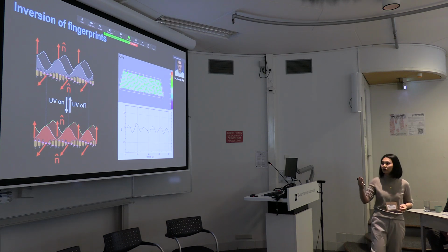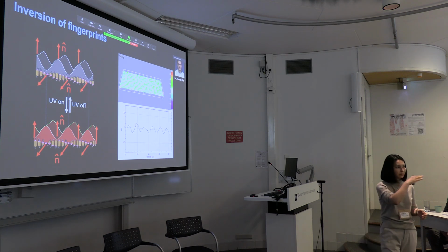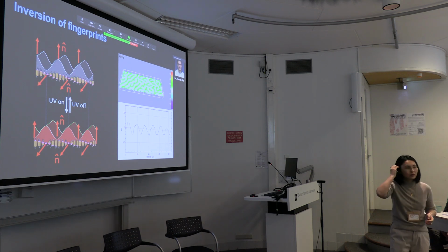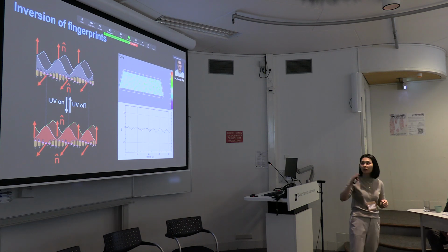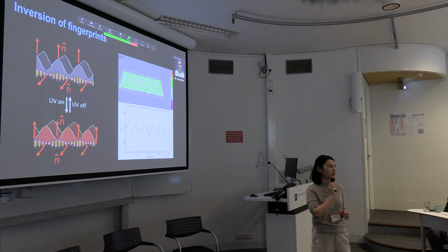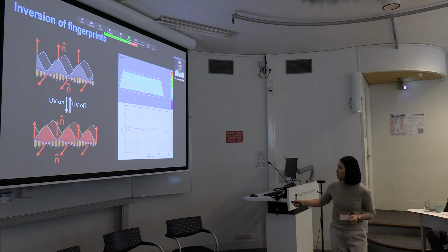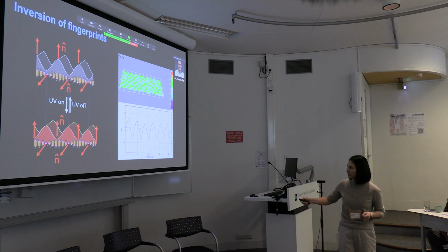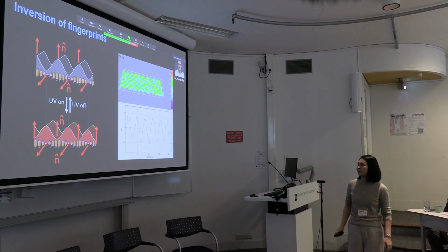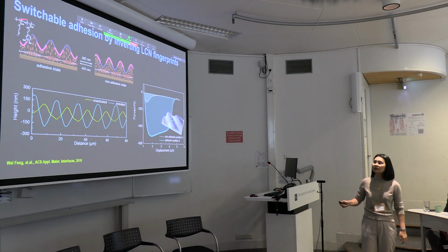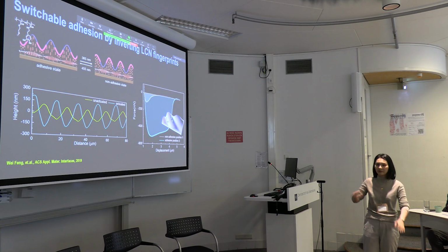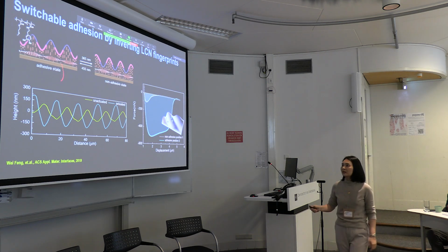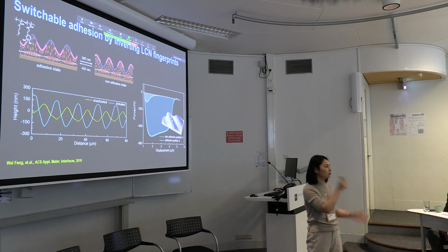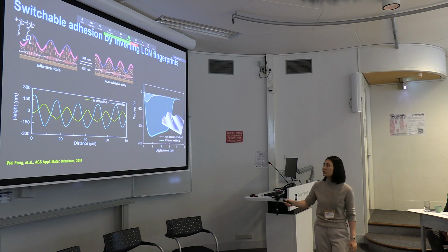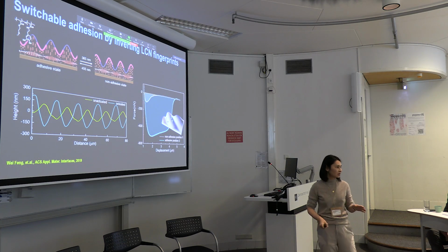In the previous video, we always started from a flat surface to a corrugated surface. But what can also be interesting is that we start from a corrugated surface, and now we inverse the surface. This means, as you can see here, the top becomes the bottom under the trigger, and the bottom goes back to the top. And we play a trick. Initially we put adhesive on the top of this wave-like structure. This adhesive is the mussel protein used to attach to rock. The top surface has the adhesive, and the bottom is non-adhesive.